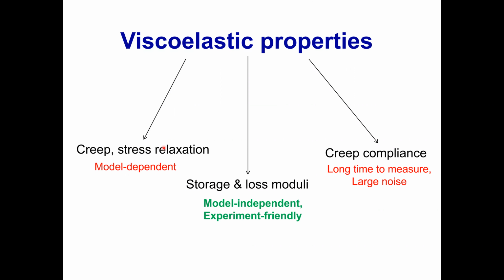Without more details, creep and stress relaxation are somewhat easier, but they are model dependent. It means that if you want to extract some quantitative information from these measurements, you need to assume some model. Storage and loss modulus is really model independent. The only thing you need, if you want both moduli, is some contact model to assume, literally to calculate area of contact. If you are satisfied with loss tangent, for example, then it's completely model independent. Contact area is not there.